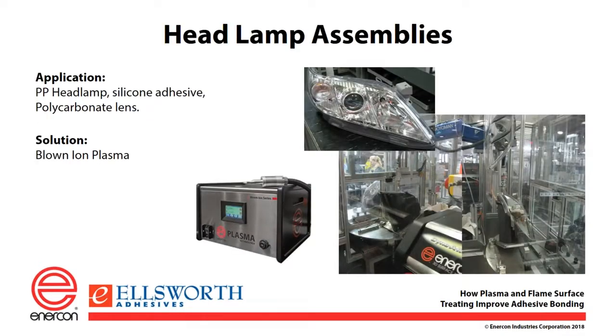The next one is one of the original automotive applications for plasma. Older cars had a terrible time keeping the water out of headlamp assemblies, and now we've pretty much eliminated that. We treat the housing prior to the silicone adhesive that's put in there, and then the lens is put on, and we have a nice seal now, and it's usually pre-treated with a blown ion system.